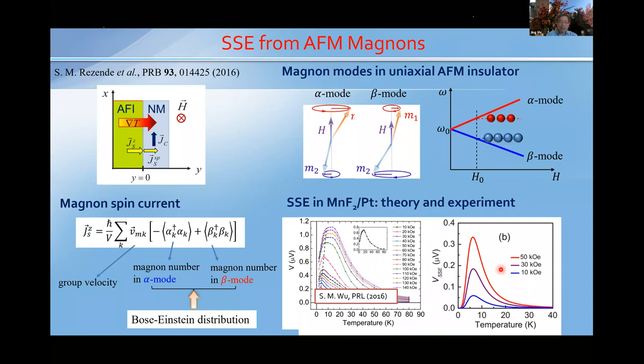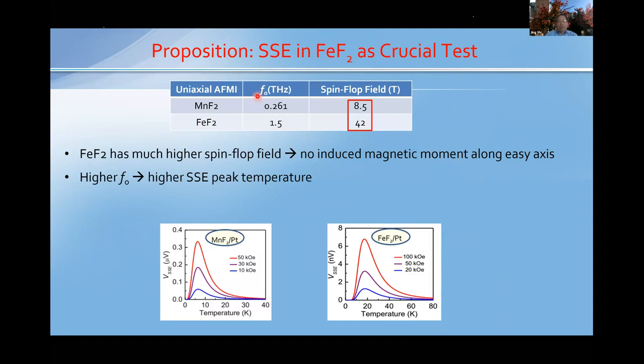Our proposition, to address the question I mentioned earlier, is to choose a uniaxial antiferromagnet which has an extremely high spin flop field, so that in our laboratory we don't have enough field to generate any large induced moment, especially at low temperature. So we want essentially zero induced moment with magnetic fields of 10 Tesla or below. We chose iron fluoride, which has a very high spin flop transition field of 42 Tesla. You have to go to the magnet lab to go through the transition.